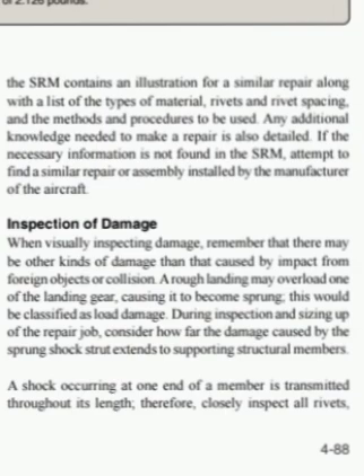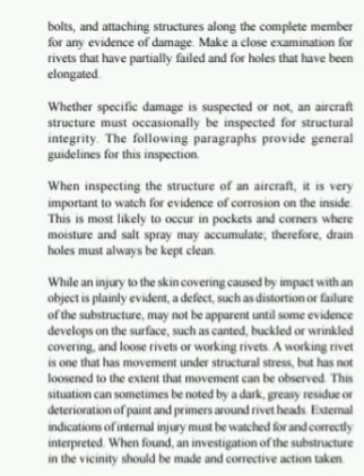Inspection of damage. When visually inspecting damage, remember that there may be other kinds of damage than that caused by impact from foreign objects or collision. A rough landing may overload one of the landing gears, causing it to become sprung. This would be classified as load damage. During inspection and sizing up of the repair job, consider how far the damage caused by the sprung shock extends to supporting structural members. A shock occurring at one end of a member is transmitted throughout its length. Therefore, closely inspect all rivets, bolts, and attaching structures along the complete member for any evidence of damage. Make a close examination for rivets that have partially failed and for holes that have been elongated.